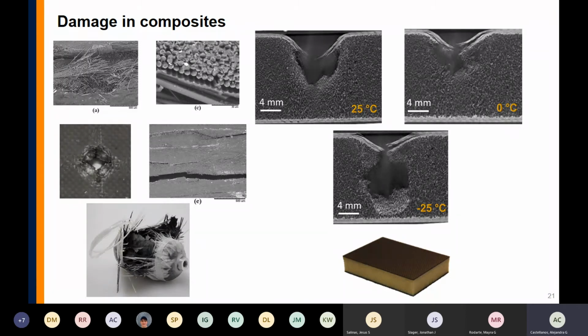Because when a composite fails, it fails catastrophically. It won't tell you, okay, it's going to start leaking and then it's going to fail. No, when it fails, it's as you can see here in these pictures. And on the pictures that say 25 Celsius, 0 degrees, and minus 25 Celsius, those are micro CT scans of the sandwich composite at three different temperatures. This sandwich composite was impacted with the striker, and then we evaluated how the temperature affects the sandwich composite. As you can see here, as the temperature decreases, the penetration of the striker through the foam starts to increase, which means that at lower temperature, the material becomes more brittle.